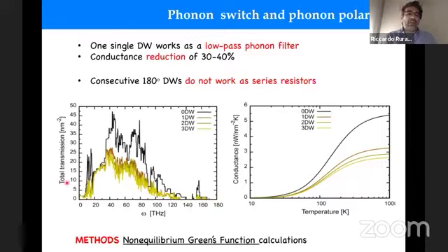You have a transmission spectrum, and here we can see that the scattering that we already described with molecular dynamics essentially comes with high frequency phonons, and low frequency phonons do not really see this boundary, and then they go through it almost unperturbed. And then what is perhaps more interesting is this other graph here, where you see, in a different way, what I was discussing before.